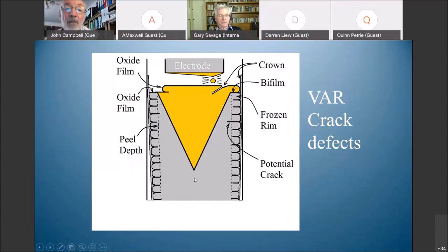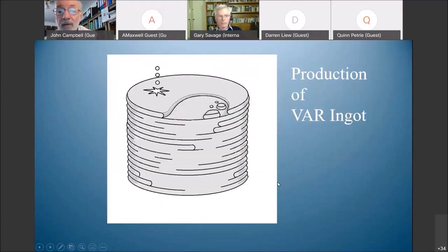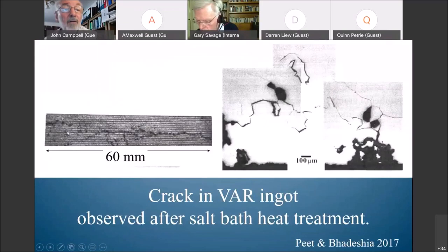So here we have this extremely expensive steel with cracks 60 millimeters long in it. It's very difficult to find the cracks because they're very thin. They were put in vacuum, so there's not that much oxygen. So the bifilms are extremely thin, so you can't find them, but they're still very efficient cracks. And here is one of these cracks. Look, 60 millimeters long. This is the thing under the microscope. It's a very messy sort of crack. This was observed by people at Cambridge University when they bought a bit of steel, and they bought the best steel they could afford, thinking it was going to be free of defects, and they found this 60 millimeter crack in it. Just totally remarkable.